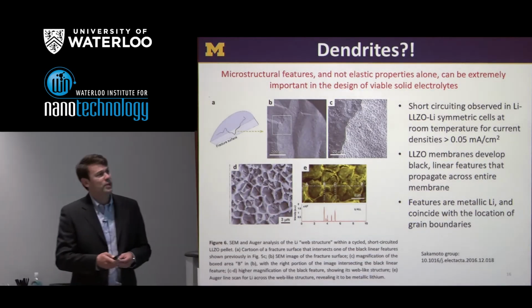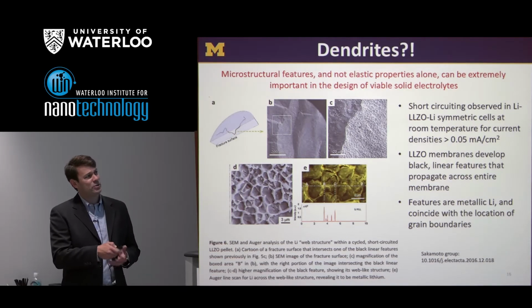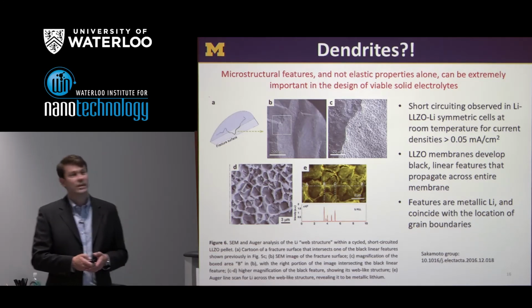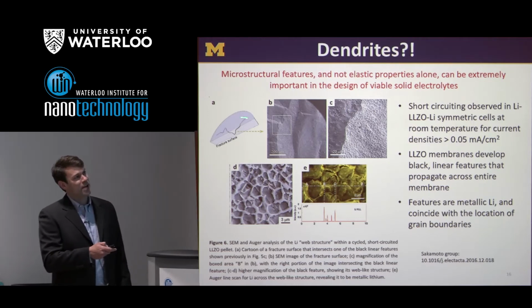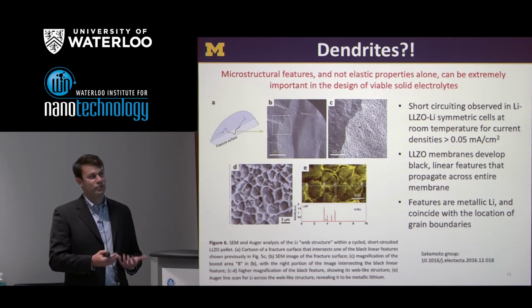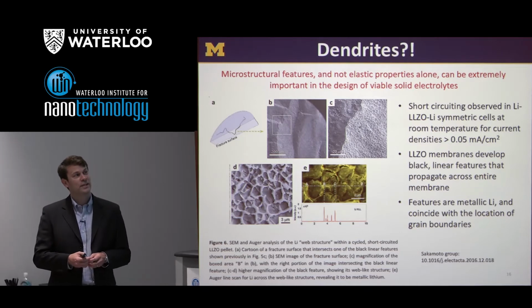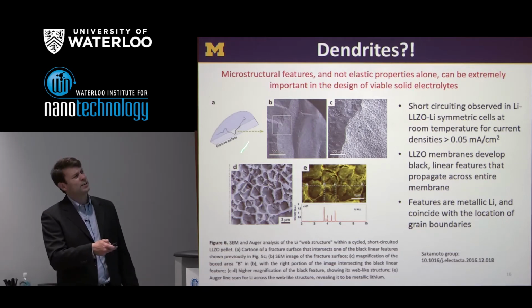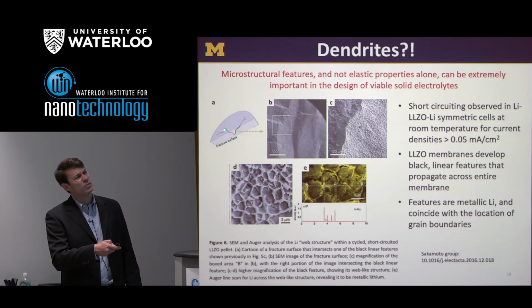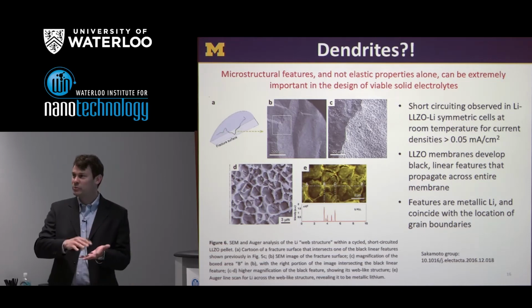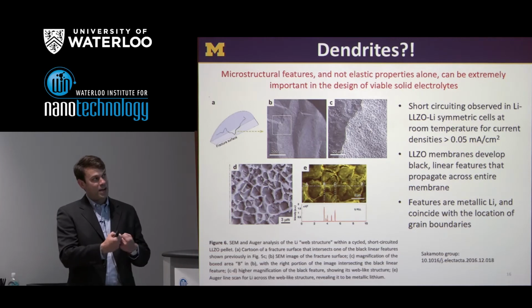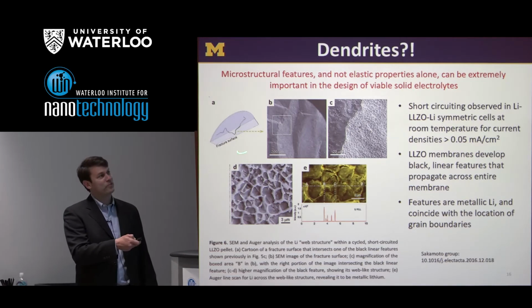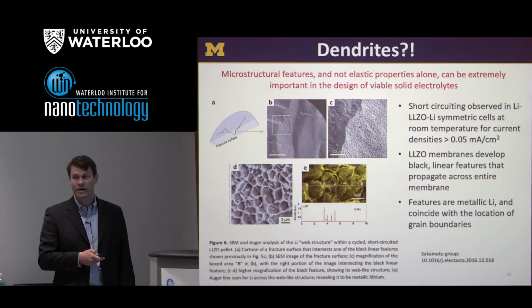Jeff Sakamoto's group has recently reported that when you take an LLZO pellet and cycle it in a lithium-LLZO-lithium symmetric cell at, I'd say, a modest current density, bad things happen. During cycling, it appears as though a short circuit has formed. Taking the cell apart and looking at the LLZO membrane, what is seen are these black linear features, which would be on both faces of the pellet. And if you crack the pellet and get lucky enough, the fracture surface will intersect this black region. That's what's magnified here to the right in SEM.